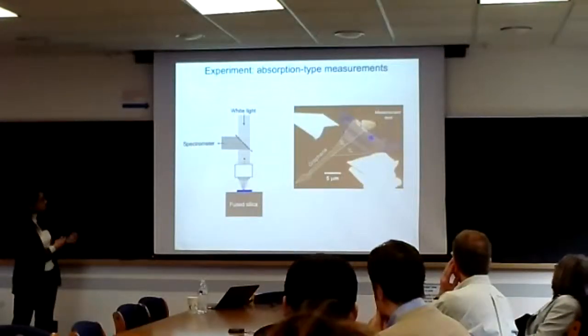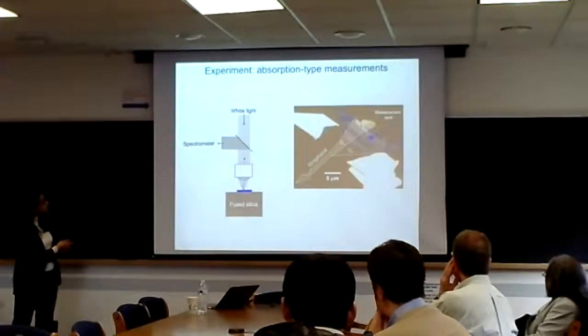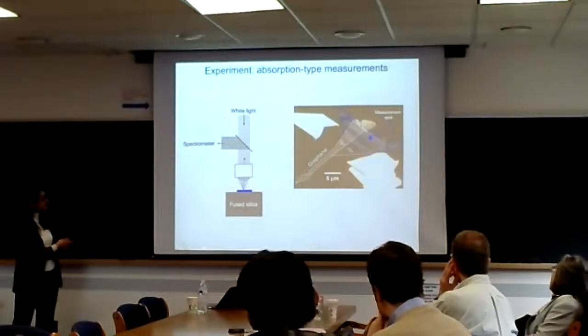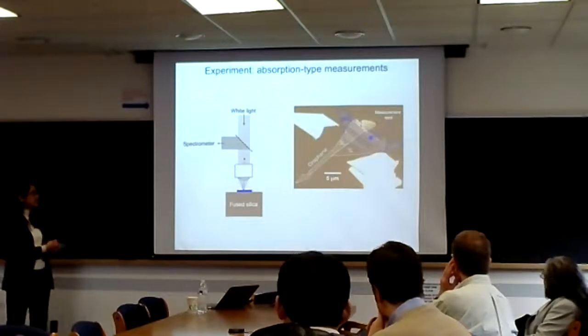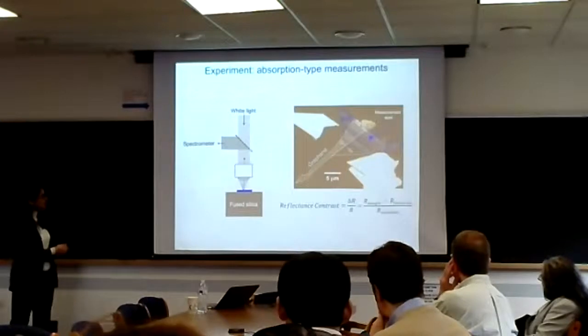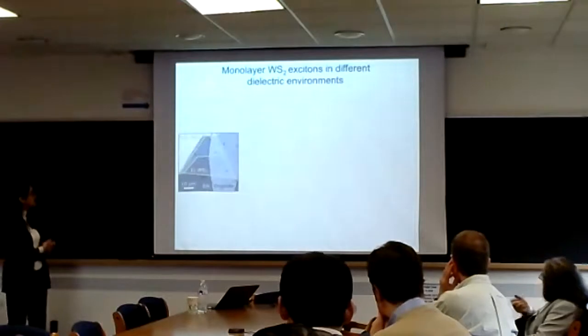Of course, samples have improved over the years. You can make much larger ones now. So you have WS2, a monolayer of the semiconductor that's in blue, sitting on top of the transparent substrate, and we partially cover it with graphene of different thicknesses, and we go from spot to spot. We are limited by the diffraction limit here, so something like a micron, and measure the exciton states in these different dielectric environments. So for all practical purposes, you can read this reflectance contrast as just the optical absorption here.